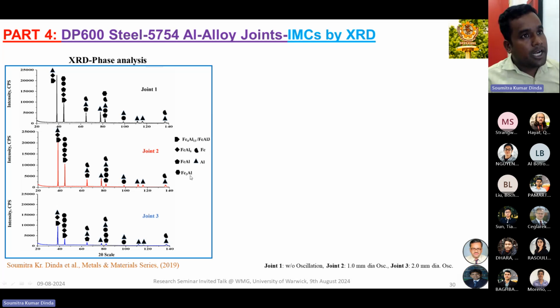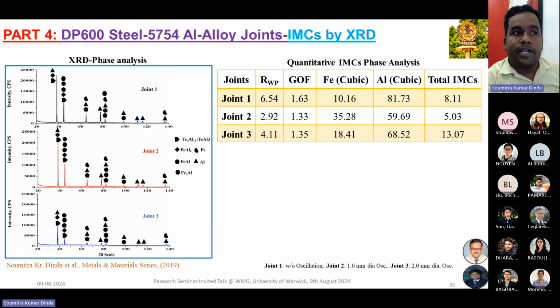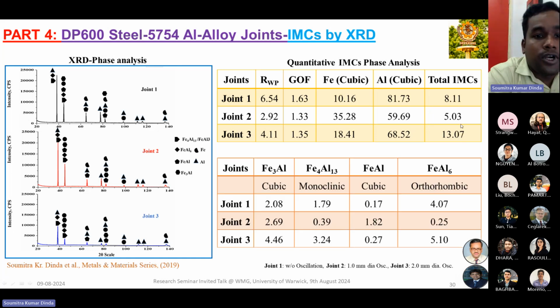But we did the Rietveld analysis to get quantified data, and we found that the total intermetallics first decrease for joint 2 and then increase again. These are the four different types of intermetallics: Fe3Al, Fe4Al13, FeAl, and FeAl6. We get the individual percentage of intermetallics formed for the different welding conditions or joints. But room temperature XRD does not give us proper individual peaks.